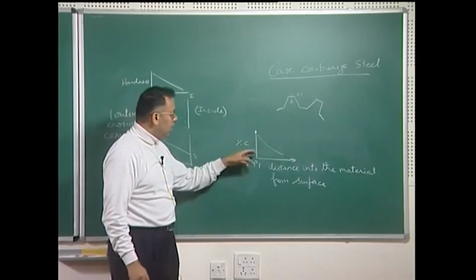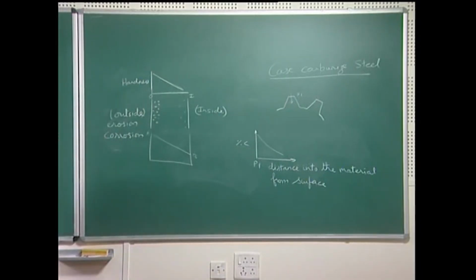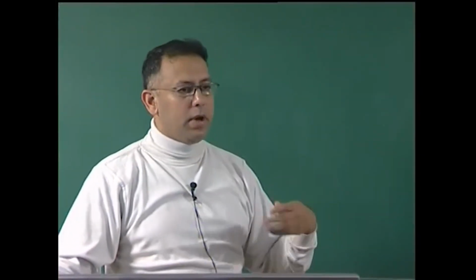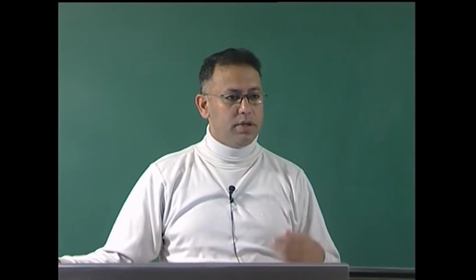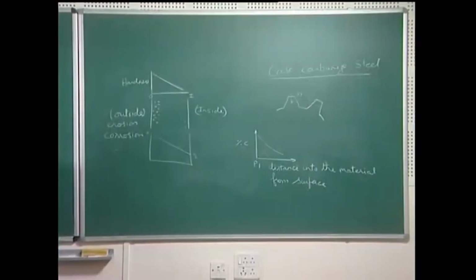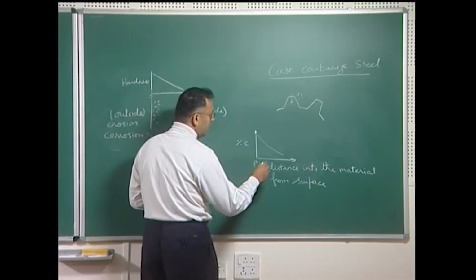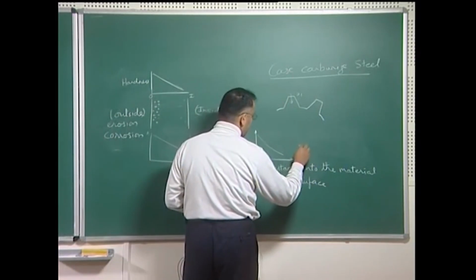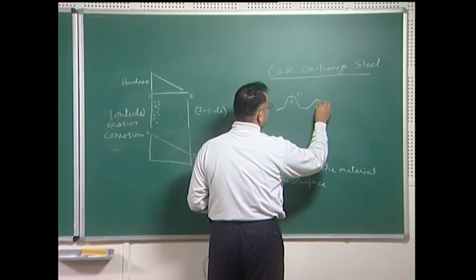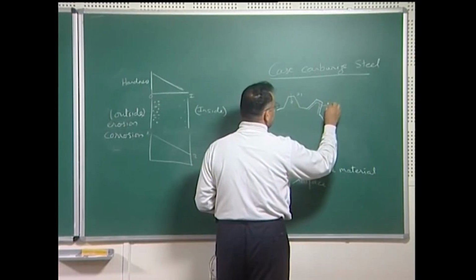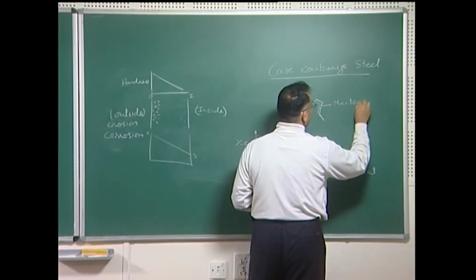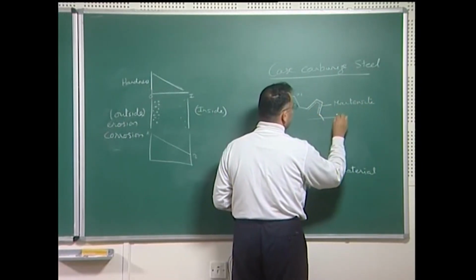Now, the important point is that I take a material with a certain amount of carbon in it. For instance, I would take 0.2% carbon steel, then I would impose a carbonaceous atmosphere on the surface, which will now allow carbon to slowly diffuse into the material, and after some time I will stop the carburization process, cool the material, later on take the material to high temperature and quench it. In this process, what would happen is that the surface would have a high carbon martensite, while the interior would have a microstructure which is like pearlite. So, I have an outer surface microstructure, and an interior microstructure which is more like pearlite.